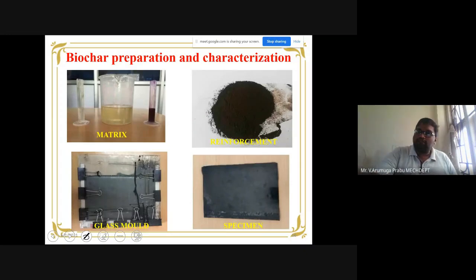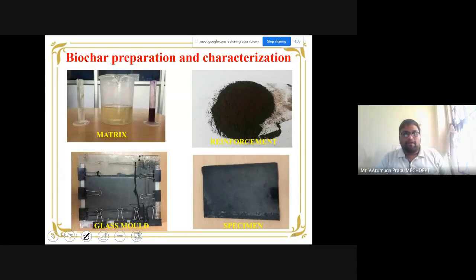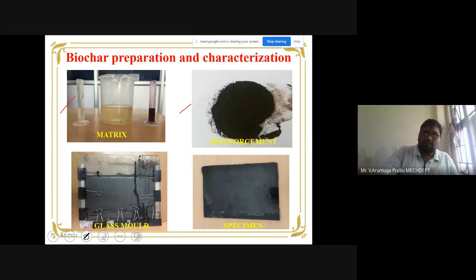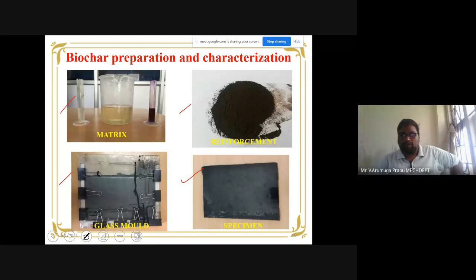This diagram shows how we are preparing the composite with the biochar. The first one is the matrix, which, as usual, is the polyester matrix. Then the reinforcement is your biochar. See here, this black one is none other than your biochar. And this is the solution dispersion method, which I pointed out a few minutes back. This is a glass mold, covered on all sides except the top. Through the top opening, the mixture of your matrix and the reinforcement is poured into the glass mold, and the mold is left for curing. Your final specimen is obtained in a rectangular or square form, depending on the size of your glass mold.